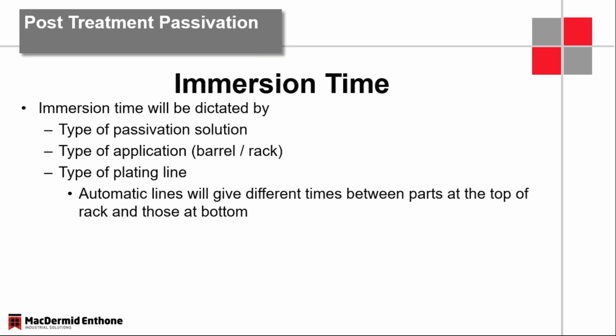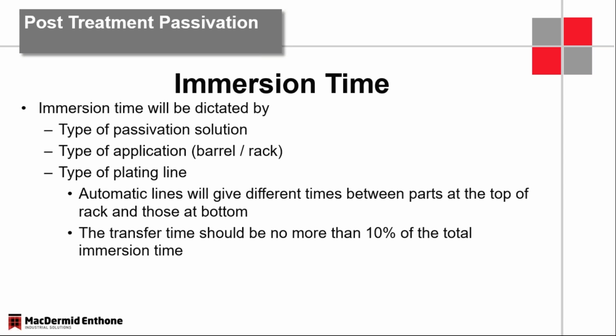And then you have to take into account transfer time. It slowly comes out of the tank, it slowly moves over to the rinse tank, and slowly goes into the rinse tank. That transfer time needs to be taken into account of your total immersion time, because that part hasn't been washed off yet. You've still got chrome on that surface, and that reaction is still taking place.